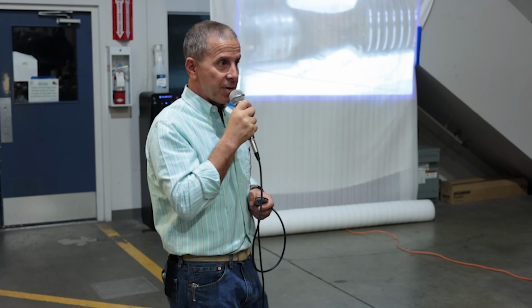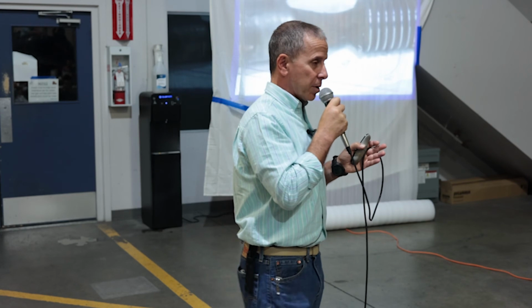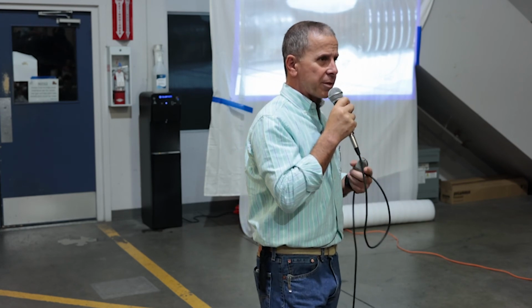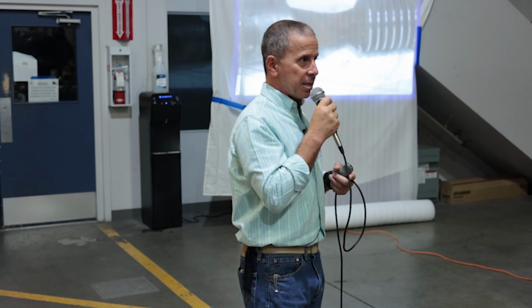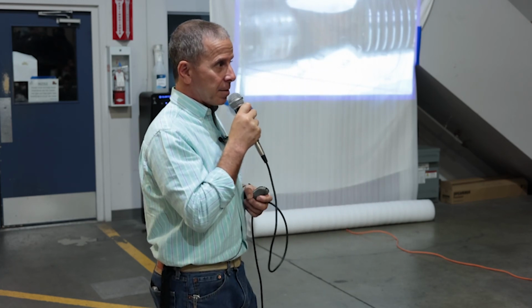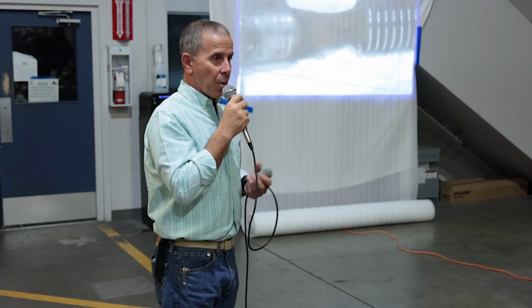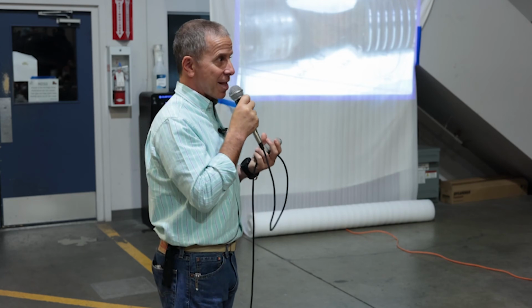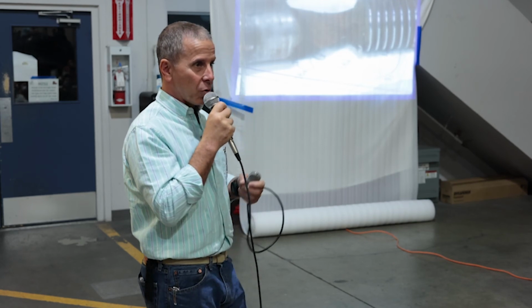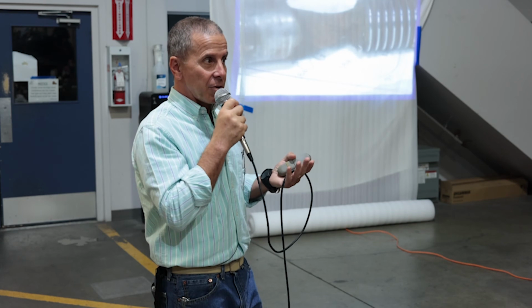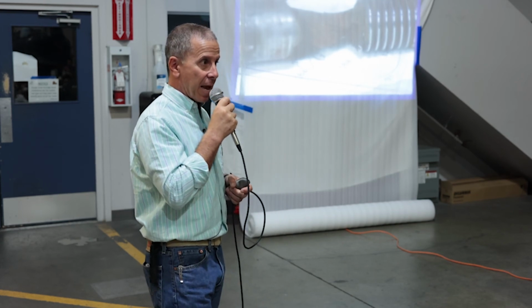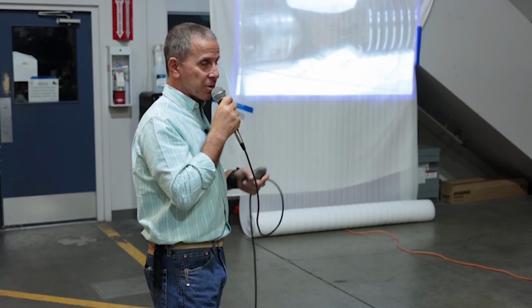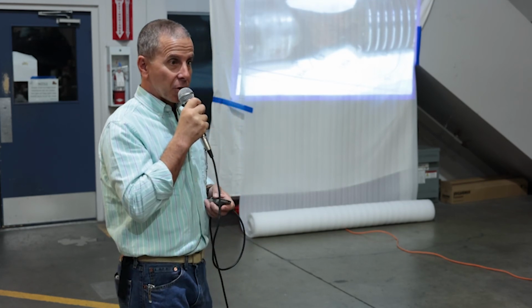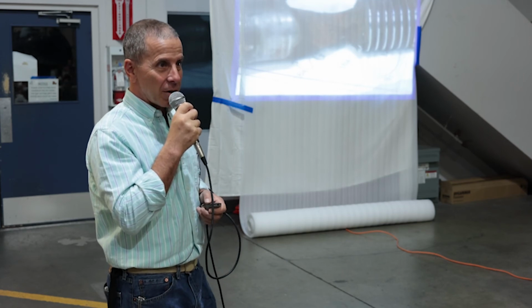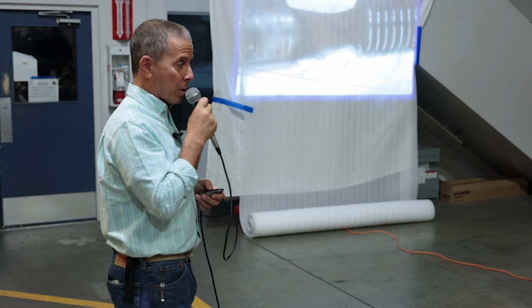Now, you might have some telltale evidence of this. When crevice corrosion occurs, it usually creates a brown staining, sometimes called tea staining or coffee staining. It's a dark brown, typically sort of a rust stain that will emanate from that stainless steel fitting. So if you see this sort of drip or trickle or line of rust coming out of a stainless fitting where it passes through some structure, that should definitely get your attention. It means that stainless has gone active, at least in some location where it passes through that substrate. So that's the only clue you're going to get that this is going on. Don't ignore it. It's absolutely worth looking at more closely.